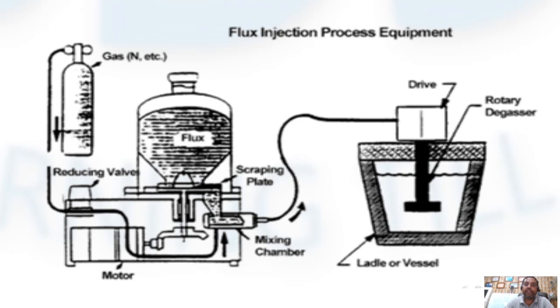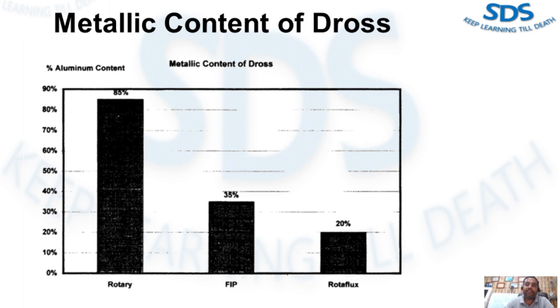One of the principal benefits of combined flux injection and rotor dispersion technology is the effect on dross content. Any fluxing or rotor dispersion creates dross. This is because not only is there some turbulence involved in the metal bath, but more importantly oxides are brought to the surface. Despite the difference in metallic content of the dross resulting from rotor degassing and flux injection, each alone and in combination, in essence application of the proper flux compound reduces the dross, resulting in a lesser quantity of dross and subsequently lower metallic content of the dross and remains.